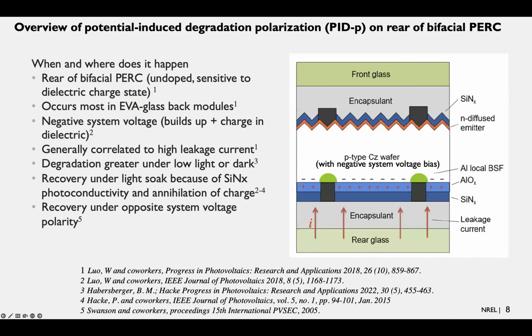Okay, so in order to fully explain the results, I need to give a little primer on one of the degradation modes we found, and that's potential induced degradation polarization. And this can occur on the rear of bifacial PERC. It happens on the rear of PERC because the rear of a bifacial PERC cell is undoped, and it's very sensitive to the dielectric charge state.